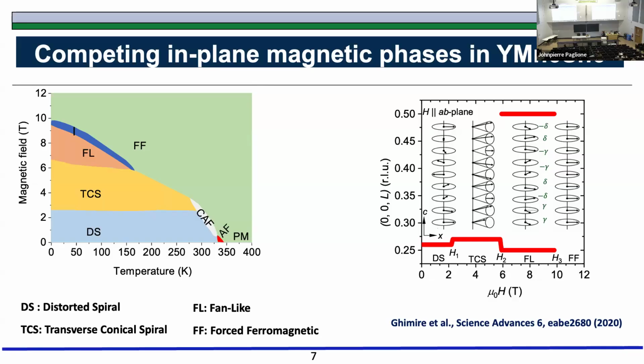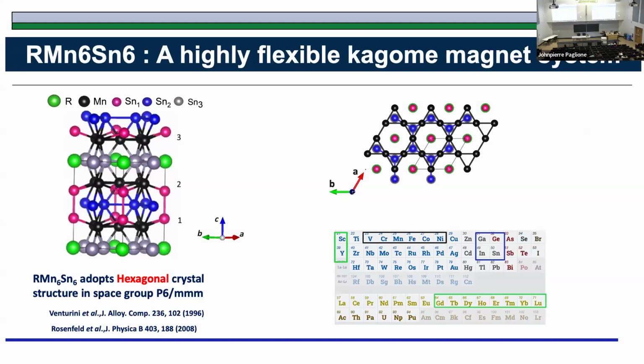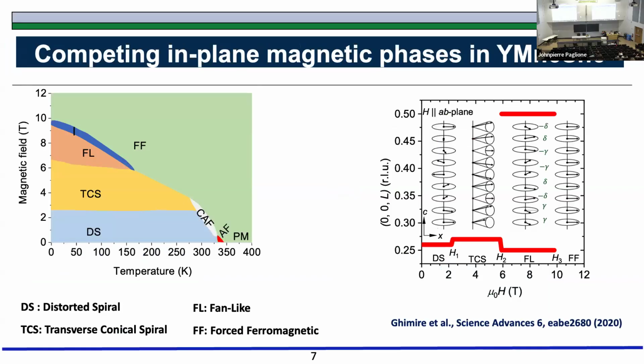Okay, so to give you the context, in each of these manganese layers, the spins are parallel. So they are ferromagnetic in the plane, all pointing in the same direction. When it goes to the next plane, it is also parallel, but in the third plane, it's anti-parallel, with double layers moving together, right? One pair pointing in one direction, and the next two layers pointing in the opposite direction. That's how you get the antiferromagnetism in this case. And then you apply a magnetic field in the plane. Then you generate a lot of different magnetic phases. This is DS, distorted spiral. This is transverse conical spiral. This is a fan-like phase. Some incommensurate phase, and then it becomes a ferromagnet finally.